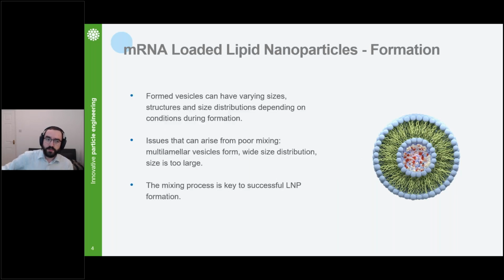Now, these formed vesicles, depending on that mixing process, can have various different sizes, structures, and size distributions depending on how that mixing process is controlled. For instance, if your mixing hasn't been controlled properly, you can end up with what's called a multilamellar vesicle. So rather than just one nice individual wall, as we're seeing in that diagram there, you can have walls within walls within walls, which of course, when you're trying to release something in a predictable way, is less than ideal. You can also have wide size distributions. When you're injecting something, you want to be able to predict where it's going to go and how it's going to behave. Having those uniform sizes is very important.